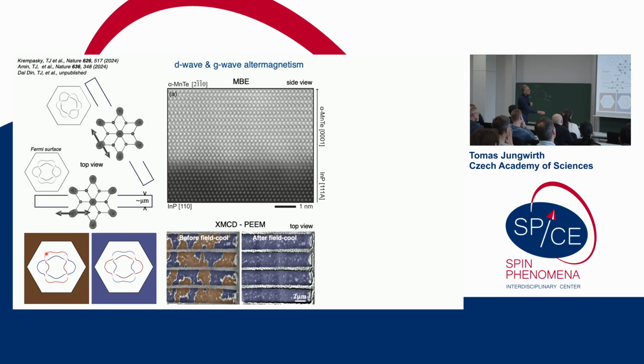So how to distinguish between the time reverse domains is by performing a field cooling experiment. They are field cooling the sample in one or the opposite direction. So this is the virgin sample, where you have a 50-50 mix of one domain and the time reverse domain, corresponding to these 2 Fermi surfaces with opposite spin polarization. So you would not be able to measure spin resolved ARPES. But if they do field cooling, they can prefer one, and then they can choose. It could be either brown or blue, depending on the sign of the magnetic field they apply during field cooling.